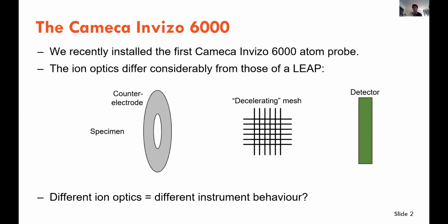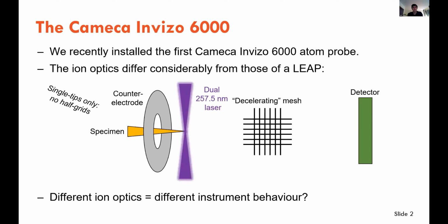So here's a basic schematic of the key elements. The first difference that should stand out to everybody is that the specimen passes through a counter electrode rather than being adjacent to a nearby local electrode. One big consequence of this is that the Invizo 6000 can only accept single tips, no half grids. The specimen is then irradiated by dual deep UV lasers, and due to the significant difference between the specimen and the nearby electrodes, there's no voltage pulsing for this instrument.